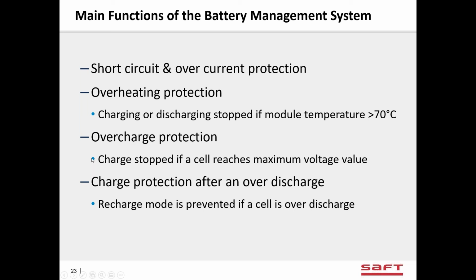Another one that's interesting with lithium-ion is if the battery is over discharged. When I say over discharged, I'm talking about less than 2 volts per cell for most of the batteries. LTO, you can go a little bit lower than 2 volts per cell, but below 1 volt per cell for sure, the battery starts to dissolve the copper that's on the anode, and the copper can become a short circuit. So if it's been at a low voltage for an extended amount of time, you have to prevent the discharge or prevent recharging.